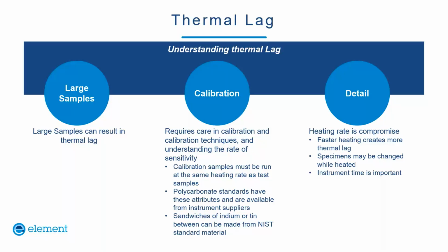Polycarbonate standards have attributes similar to polymer samples and are readily available from instrument manufacturers, but none are officially traceable to a national standards body like NIST. These materials can also change over time or with exposure to moisture. Sandwiches of tin or indium between ceramic plates can be made from NIST standard materials, but lab-to-lab variation can result if these standards aren't consistent. So work is currently being performed in ASTM committees and other places to provide robust, reproducible, and traceable standards. But getting back to the